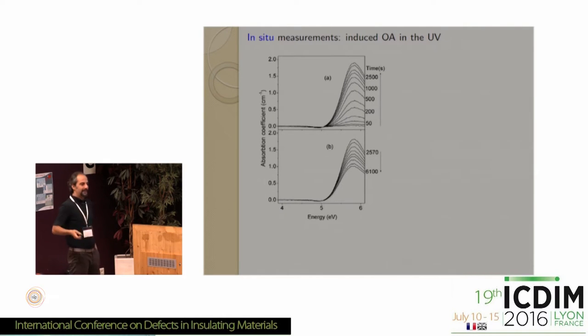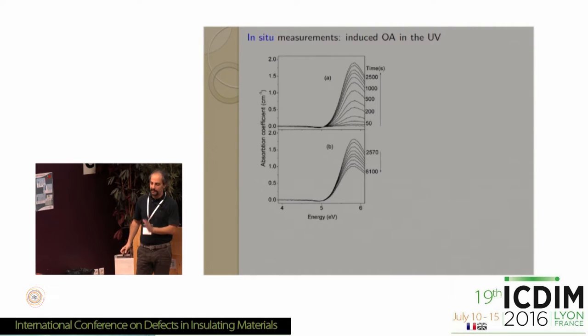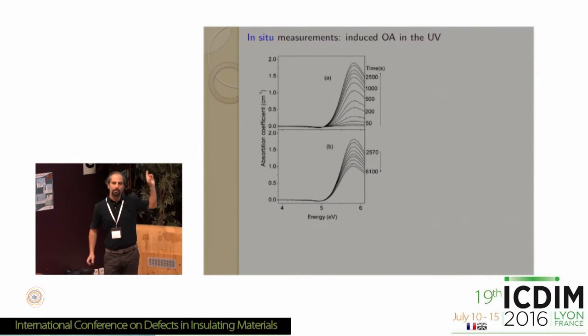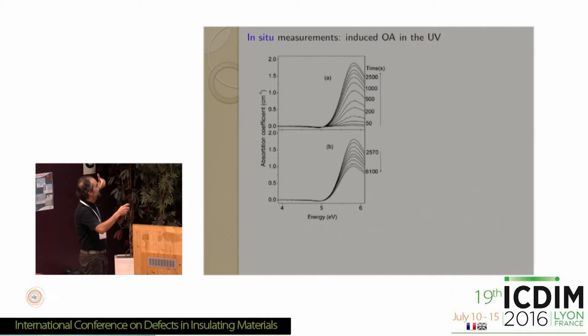This is a silica sample which is being irradiated with UV laser pulses, 4.7 eV photon energy. And in the course of time during the irradiation, we see this is a differential absorption spectrum measured at several delays during the irradiation. We see the progressive growth of an absorption band at 5.8 electron volts.